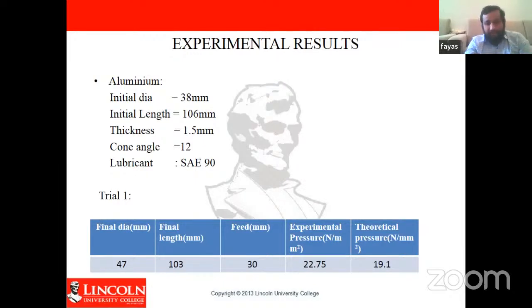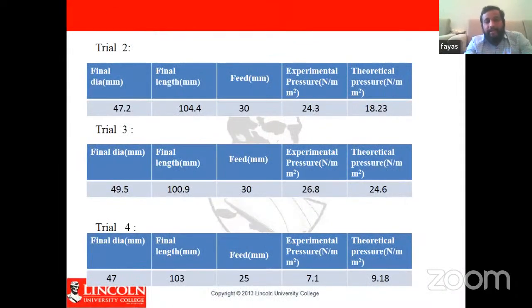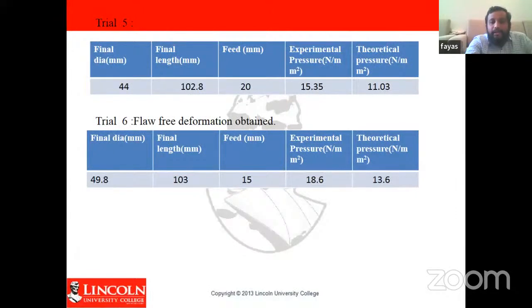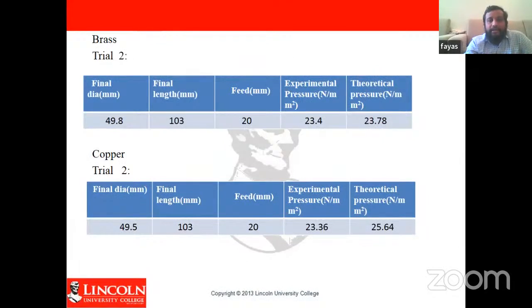Trial 1 failed. Trial 2, trial 3, trial 4, each we changed the pressure, 30, then 25, then 20 and 15. At the end, we got it at 15 pressure, flaw-free without any crack or any buckling. We got it in trial 6. Then in brass, we got it at 20 millimeter feed, in trial 2.